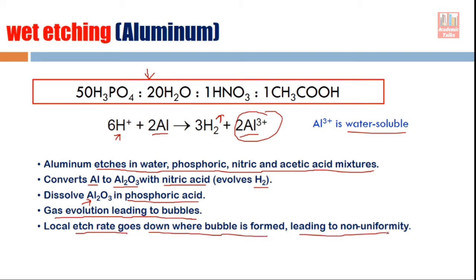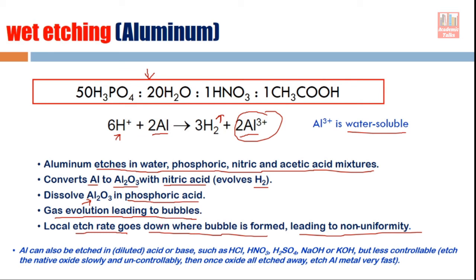Bubble formation sometimes reduces the local etch rate at certain regions, causing non-uniformity — less etching at some spots and normal etching at others, leading to variation in etch depth. To avoid this, it is always preferred to do some stirring during the etching process. Other chemical mixtures can also be used for aluminium etching, but those alternatives are less controllable, and controllability and repeatability are the main concerns.